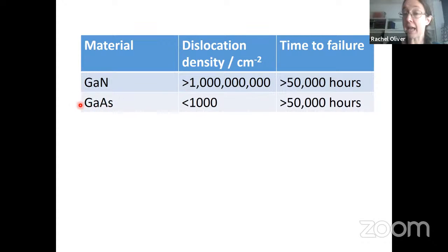If we look at a material like gallium arsenide, which is the material used to make red LEDs, well, actually it's used to make infrared LEDs, but it's a traditional LED material, the density of dislocations is only about 1,000 per centimeter squared, whereas gallium nitride, which is used to make the blue LED, there the dislocation density is orders of magnitude higher. Now we need the blue LED because it's the blue LED emitting the high energy blue light to shine upon that phosphor cap, which is then going to convert it into other colors. That process is what is going to give us white light emission, okay? So we really, really do need our blue LEDs, but they have this huge density of defects.